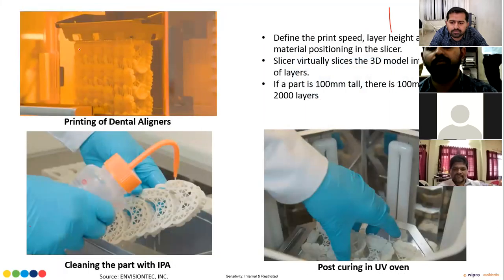So you can see they have printed a series of aligners here. In this, you can see there are almost 5 or 6 rows of dental aligners being printed, which can be stacked together. You can also stack them together by adding relevant support structure, and later you can remove them individually, and then you can clean and do all your post processing work, because here it helps you in speeding this process. You can customize it the way that you want, because every patient will not have the same type of aligners. So each patient will have a different aligner. So you can do a series of batch production for your aligners and get it done in a very fast time. If you go for the conventional way, it's a very long process.